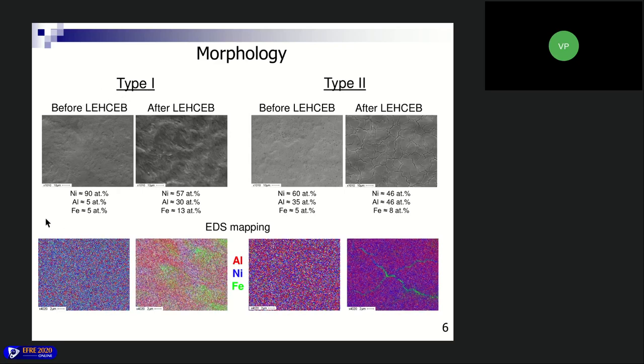So as was estimated, the thick layers don't allow us to have uniformity of the elements distribution after the electron beam treatment. That's why we tried to use thin layers, and here we have a good distribution of the elements, but we have cracks on the surface of the material.